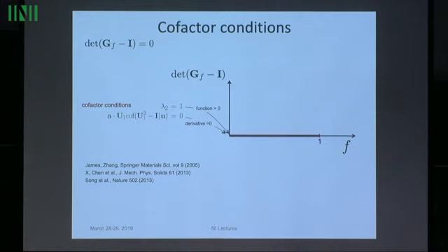Of course, every point along here gives a solution of the crystallographic theory. In other words, you can continuously change the volume fraction, and for each volume fraction, you can write a minimizing sequence which drives the energy to 0. So that's more compatibility, right? So that should in principle be useful.